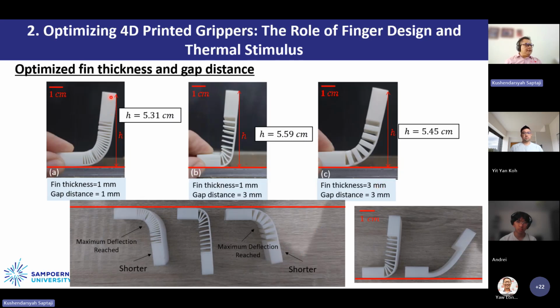After we decided the cross section, we need to find the best combination of the fin and also the gap. So we have 3 specimens with 3 different fin thicknesses and gap distances. This is fin thickness 1 mm, and the gap distance is 1 mm. This is fin thickness 1 mm, and the gap you can see is more, which is 3 mm. And this is the thicker fin, and this is the larger gap.